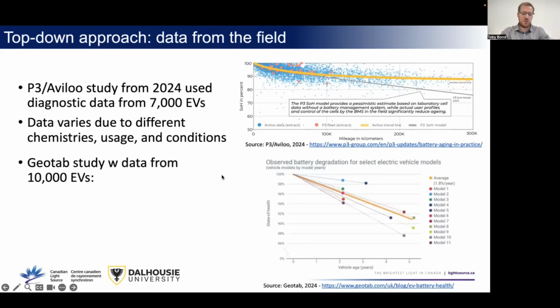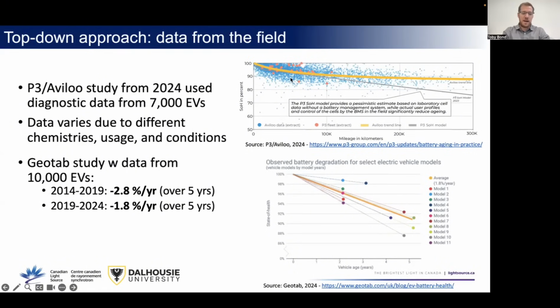There's another study from Geotab, another fleet management telematics company, involving 10,000 electric vehicles that came off lease. And they did the same kind of thing. They measured their capacity. They did this study back in 2019, so that covered the years from 2014 to 2019. And at that point, the average capacity fade was 2.8% per year over the first 5 years. So that includes that initial kind of drop. And when they did that again in 2024, that was 1.8% per year. And so that's getting really good, and it's improving substantially.